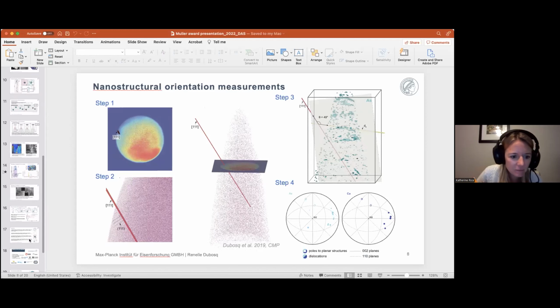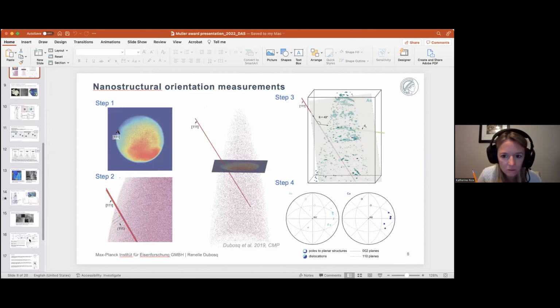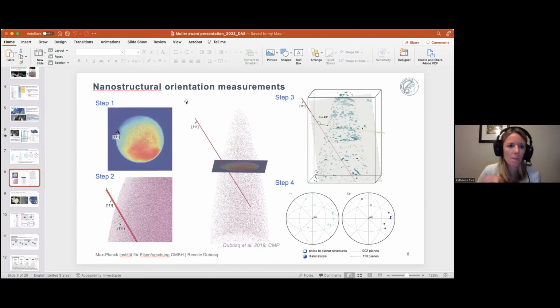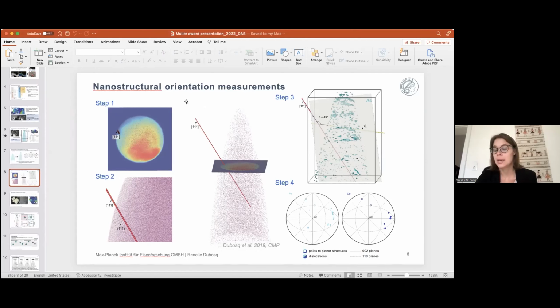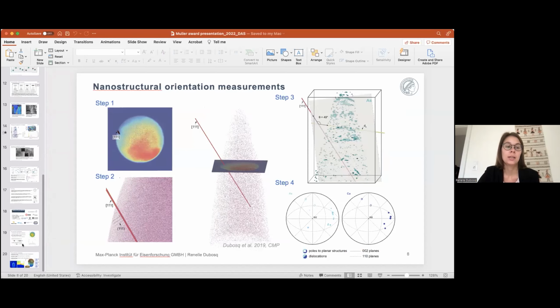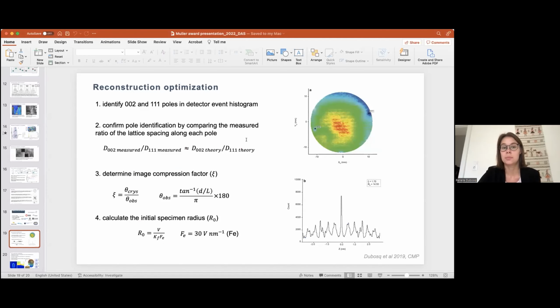So did you get an SDM from the data set that you showed here to confirm that 1-1-1 plane spacing? Yeah, I did that for every single data set that I analyzed. Here I'm just showing an example of the protocol, but for every single one I would follow this reconstruction optimization method. I would look at the spatial distribution map along each of the poles and compare their relative lattice spacing. Once I had identified them, I would calculate the image compression factor as well as the initial specimen radius to get the accurate reconstruction.